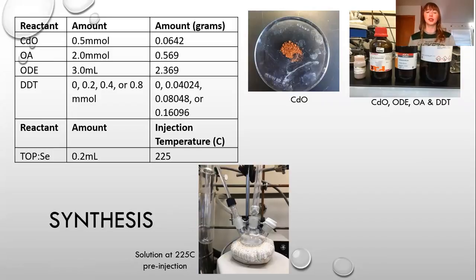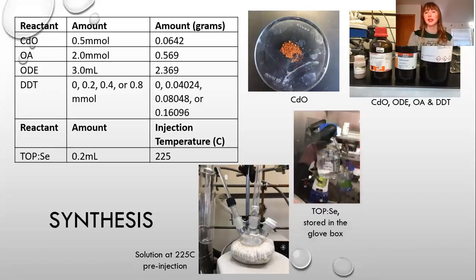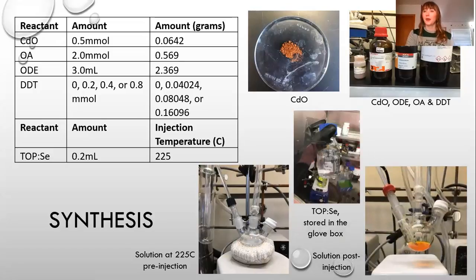But once it hits that 225 degrees for a few minutes, it becomes clear. And that's this image that you see here. This is when we add our selenide. And selenide is kept in solution in our glove box. It's this clear liquid in the bottle here. And then when we add that, it immediately turns a reddish orange color, depending on how much I add. In this picture, it looks like I added 0.4 millimoles because it's orange.